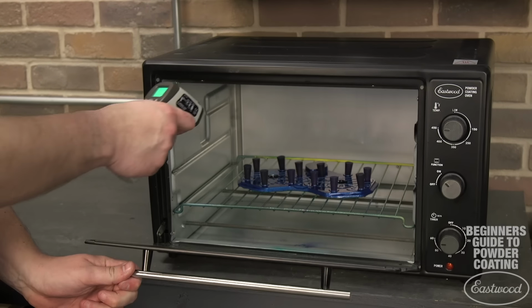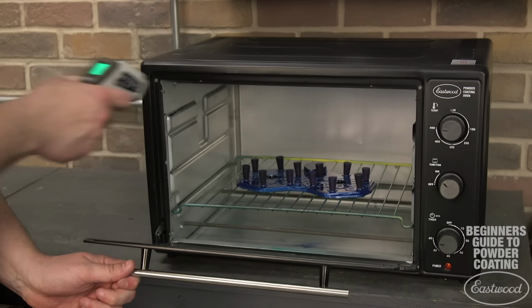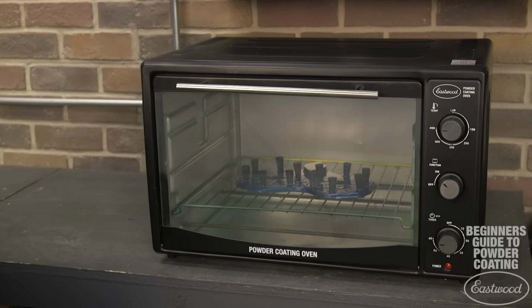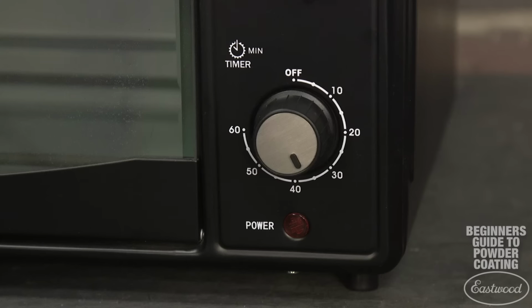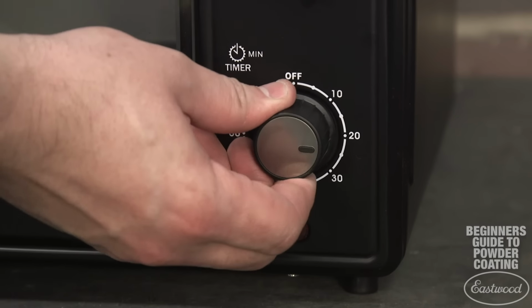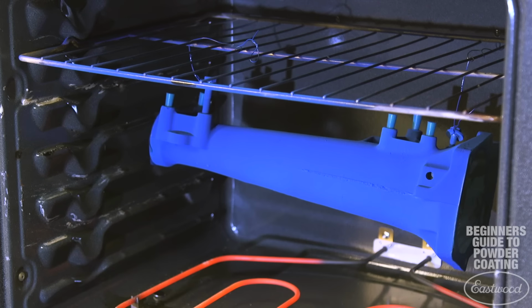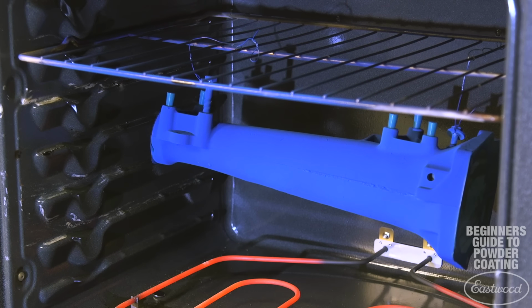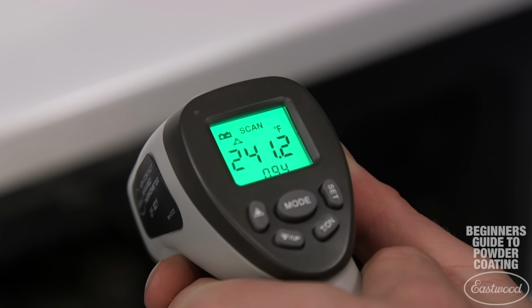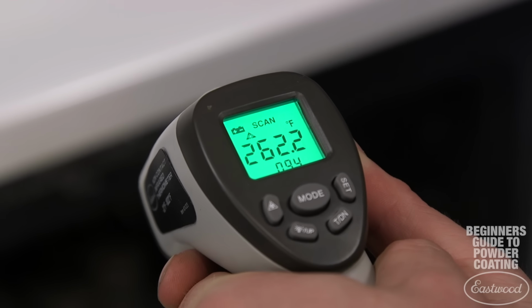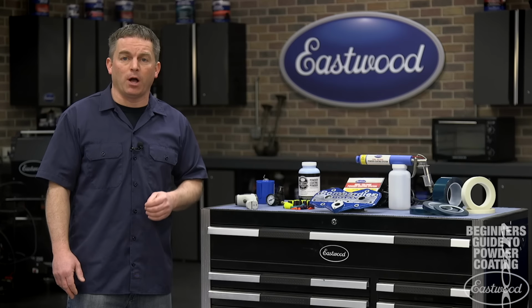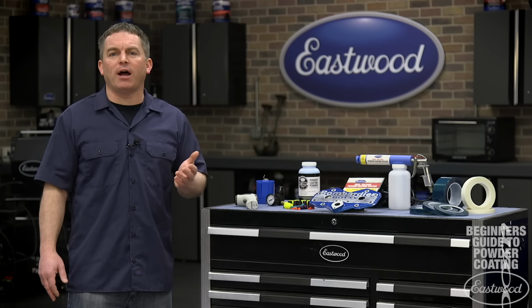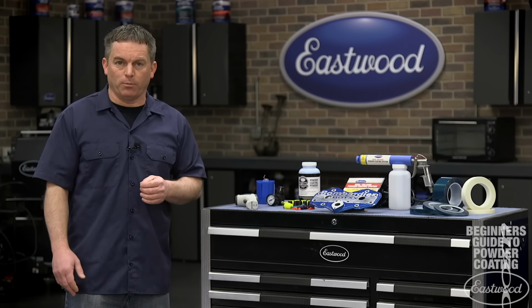A great tip that's more accurate is to use an IR thermometer to check the temperature of the part rather than the temperature of the air in the oven. When the part reaches 400 degrees, then cure it for 20 minutes. Also, heavier cast parts will absorb more heat and may take more time to reach the full cure temperature, which is another reason it's beneficial to use an IR thermometer. And remember, an extra 5 to 10 minutes of curing shouldn't hurt the powder.